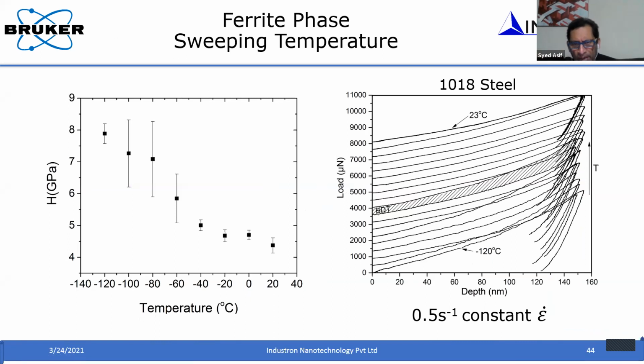For example, you can now do this experiment as a function of temperature from room temperature to very cold temperature, down to minus 120 degrees C, and then you can understand the mechanical behavior. In this case, we can observe the ductile to brittle transition in 1018 steel, where the load displacement curves give you an idea how the deformation is taking place. You can see a smooth, nice load displacement curve at room temperature. As you reduce the temperature, you start to see these serrations, typically because of the brittle behavior of the material. So you can do this pretty nicely with this load displacement curve analysis, in terms of a map or a single point, and you can observe this ductile to brittle transition.